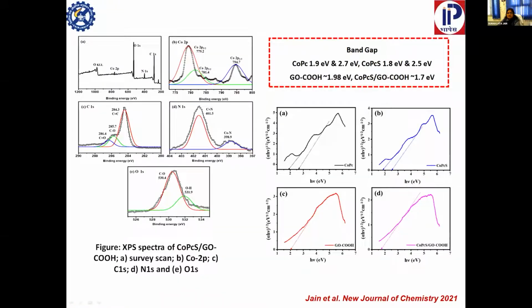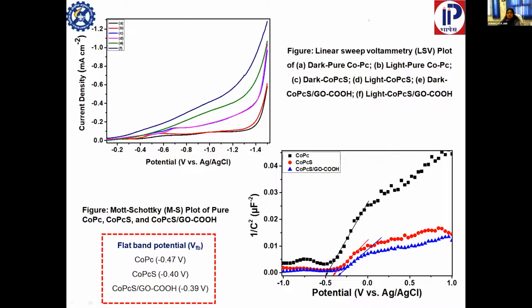Like XPS and the band gap. If we look at the band gap values in the hybrid system, the band gap values are decreasing, meaning the immobilization is further decreasing the band gap of the material, which is increasing the visible light activity. If we look at the photoelectrochemical properties of these materials, we can see that higher current density is observed in the case of the hybrid materials.